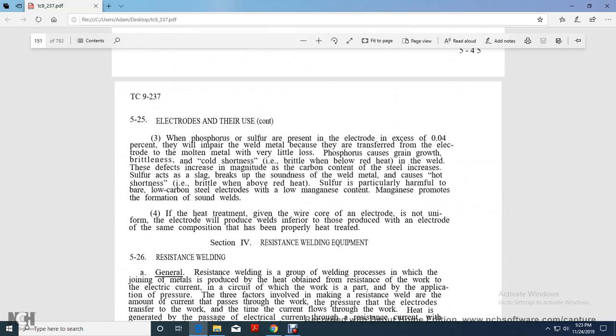When phosphorus and sulfur are present in the electrode in excess, they will impair the weldability because of the transfer of the electrode to the molten metal with very little loss. Phosphorus causes grain growth and brittleness, cold shortness, meaning brittleness below red heat in the weld. These defects increase as the carbon content of the steel increases. Sulfur acts as slag, breaks up the soundness of the welded metal, and causes hot shortness, meaning brittleness above red heat. Sulfur is particularly harmful to the weld.